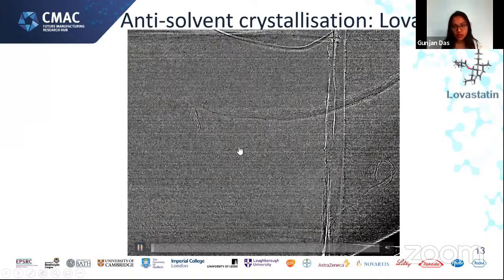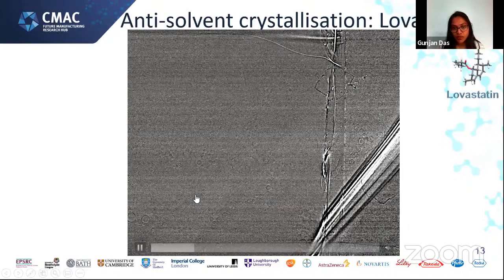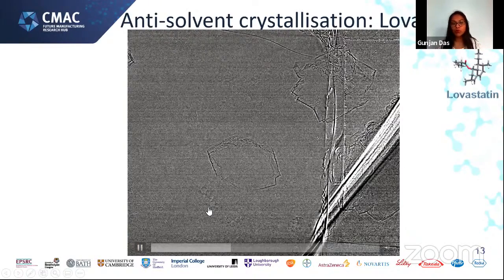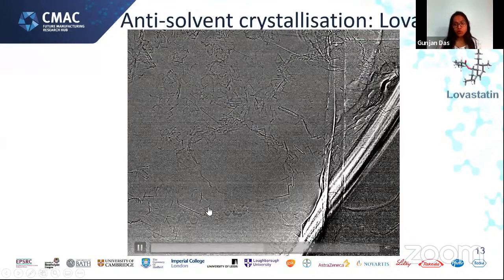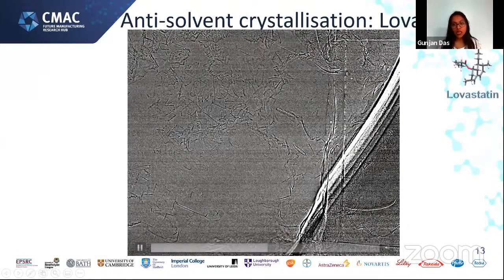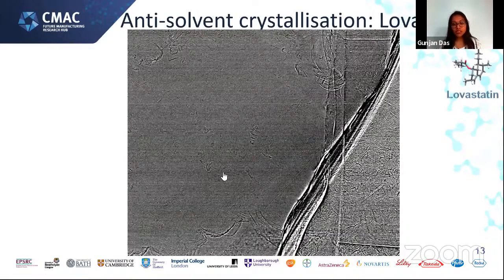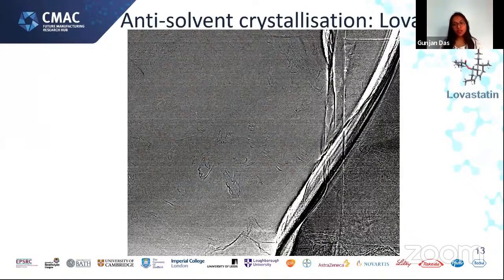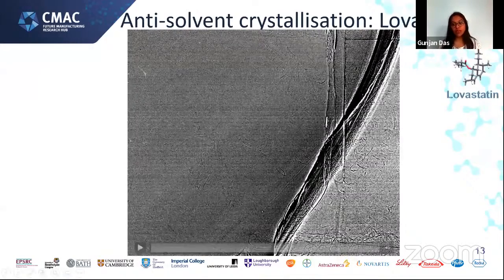Right, so what you can see now is these 2D phases growing here, and you're also able to see some spherical droplets joining and coalescing together, causing the oiling out effect, which I will speak about in a minute. But the main fact is these needle-like 2D phases do not have a starting point like needles. So maybe something can be done in the future to modify and avoid this needle-like growth behavior.